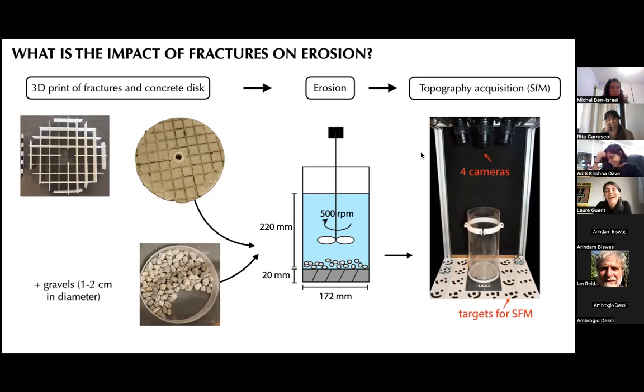Thanks. So diamond patterns, we think that because you have this angular shape, especially the ones with a very small angle, I think it is quite fragile, so that when you have impact, this is an area that will break quite easily, at least more easily than the square you can see on this figure here. So we think that this diamond shape is really easier to remove.